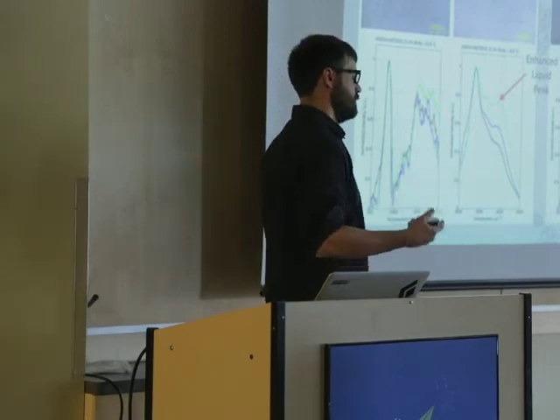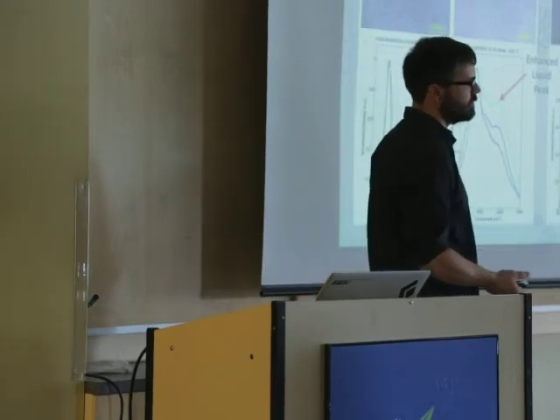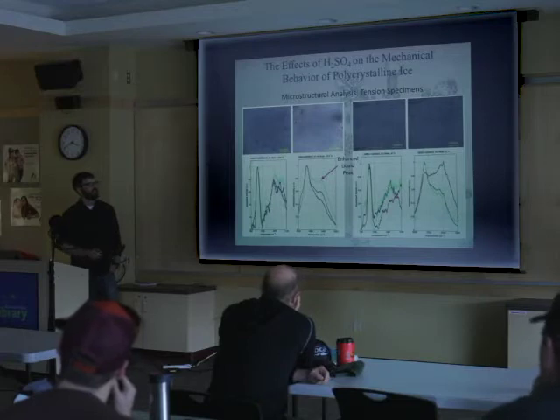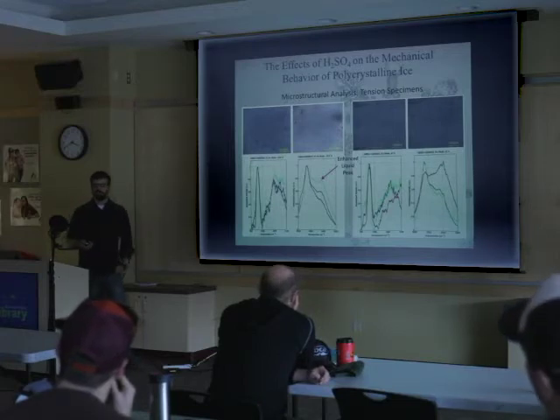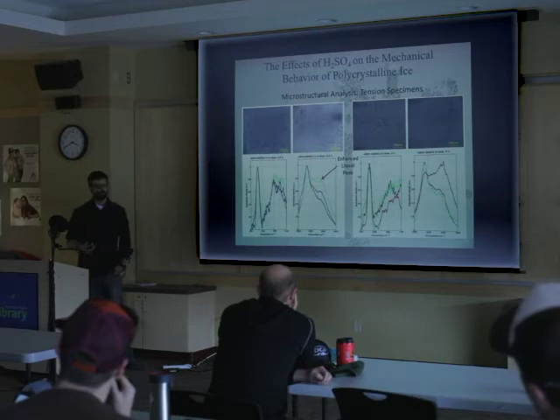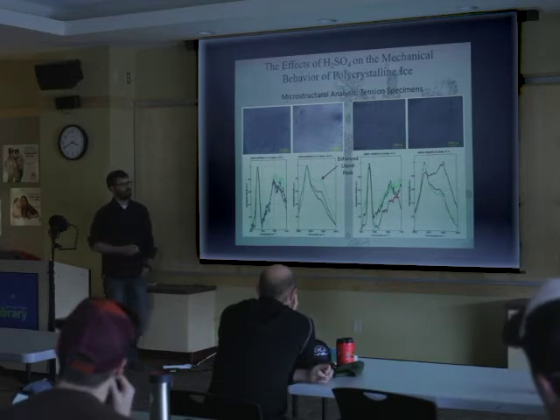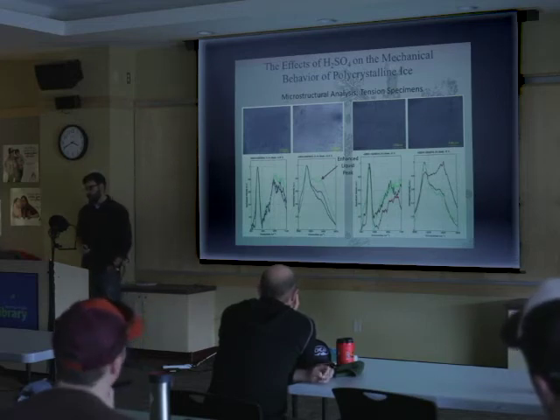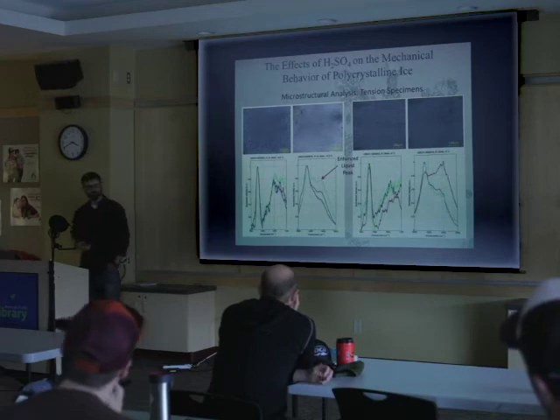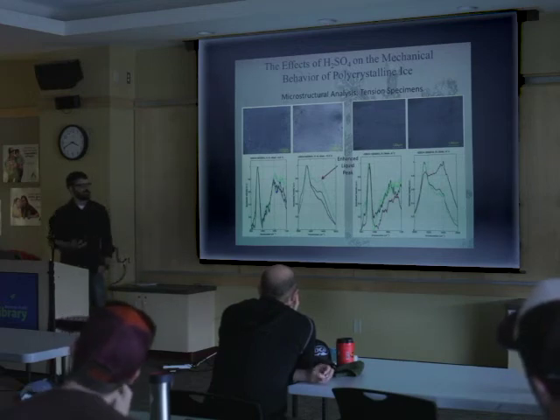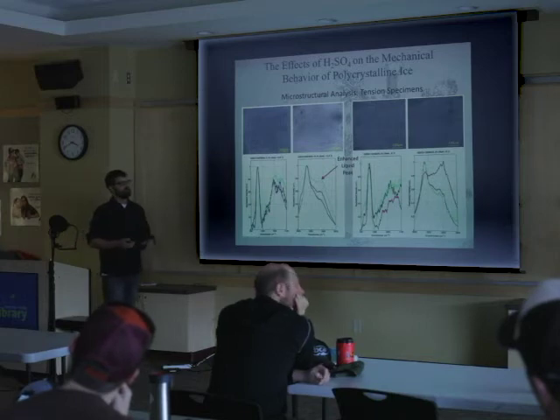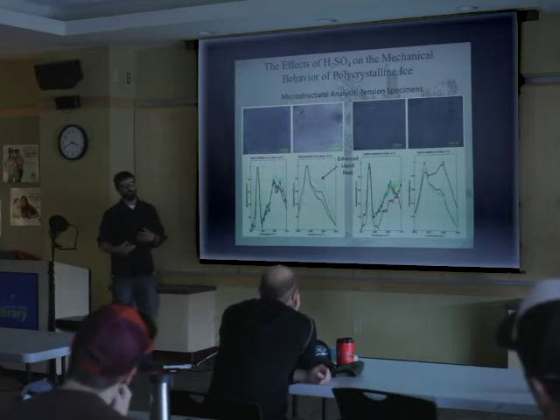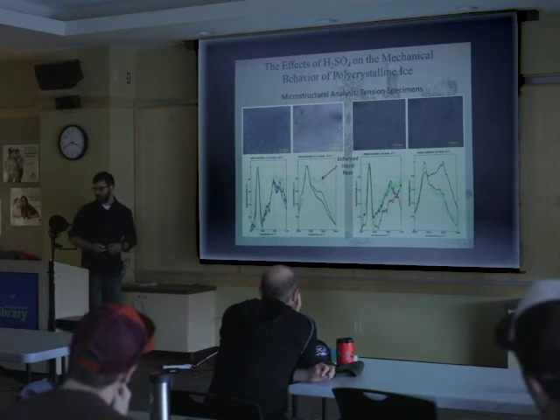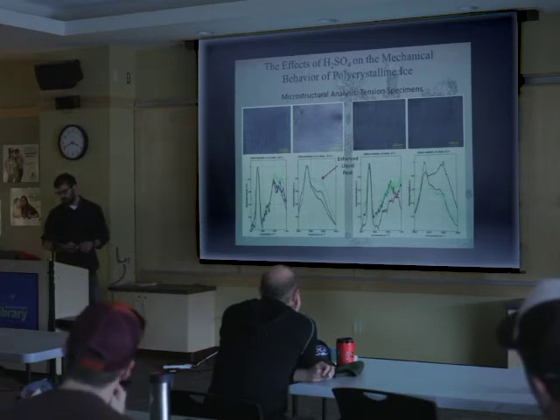You have potentially some liquid in there, and this is all related to the phase diagram of how sulfuric acid is in water, and when you apply it to ice, it comes out that you should expect to see, if you get high enough concentrations of sulfuric acid, an aqueous solution. And that's what we saw here, which I think is really pretty incredible, considering its effects on the creep behavior of the ice. So it's due to a number of different things of how you get that concentration there, but it's very obvious in the Raman spectroscopy data that it exists.